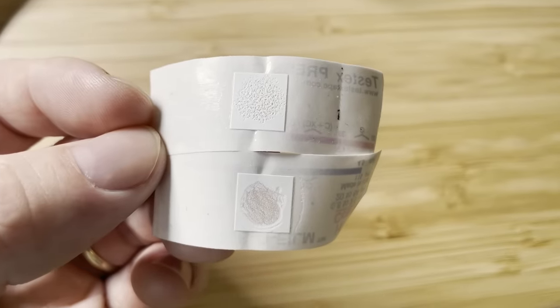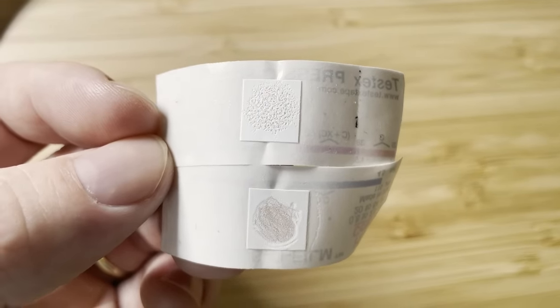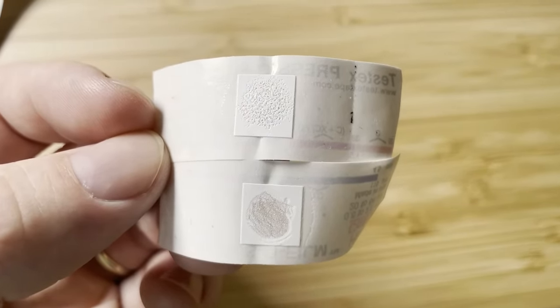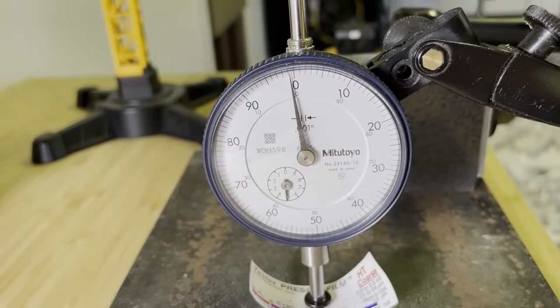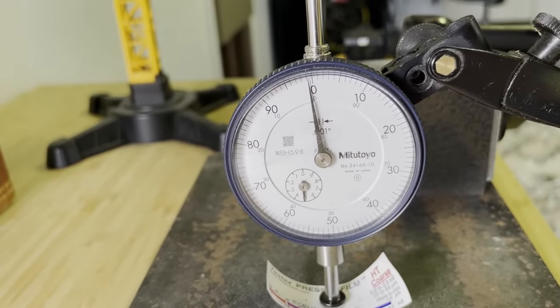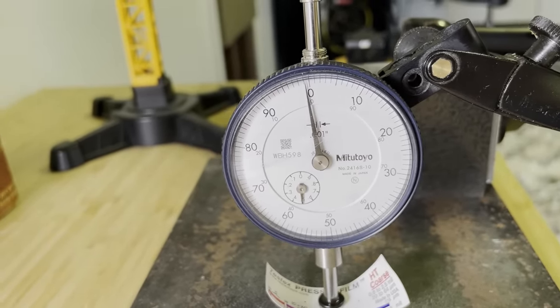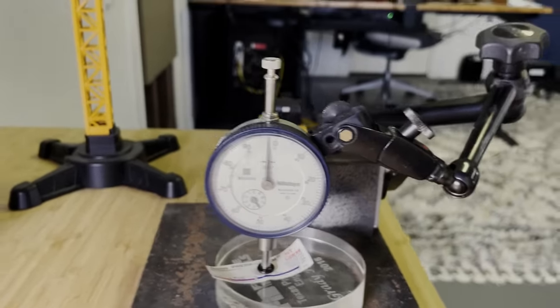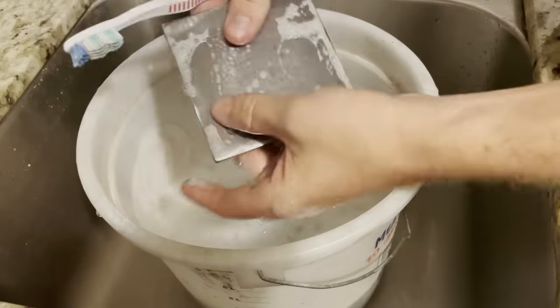Here's a look at how the foam looks after burnishing on a relatively smooth surface and a very rough one. I used my depth micrometer to measure a profile of about 1 mil or 25 microns for the smooth surface and about 2.5 mil or 63 microns on the rough one.